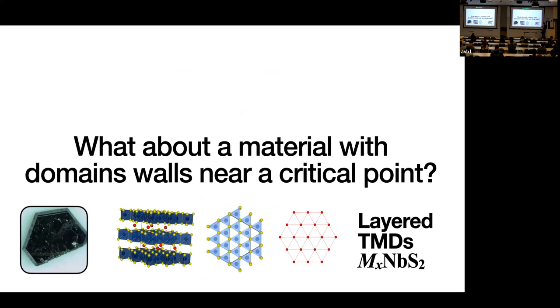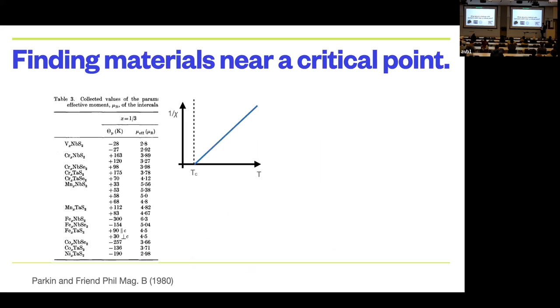I studied some materials. These are layered transition metal dichalcogenides. They're made of these lovely layers of niobium sulfide, and they're intercalated with some magnetic element, iron, nickel, whatever you want. Why did I want to study these materials? Well, back in the late 70s, early 80s, Stuart Parkin and Richard Friend were studying these materials. And they were looking at the interaction scale, this transition temperature from the susceptibility. And they looked at it for all the different magnetic elements: vanadium, chromium, manganese, iron, cobalt, nickel.